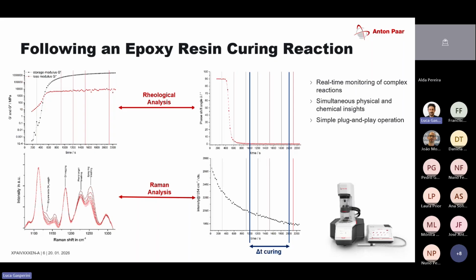So we are interested in at which time the adhesive, the epoxy resin, is completely cured. So if I take a look here, this is the loss factor. So what is the loss factor? The loss factor gives me the information if a sample is more elastic or more viscous again. So we have this phase angle here. So on a sample which has got 90% phase angle, it's very viscous, and if the phase angle is towards 0, it's very elastic. The reason for this is if I put the sinusoidal force onto a sample, it either reacts right away. So if I push something, it responds to the pushing force right away.